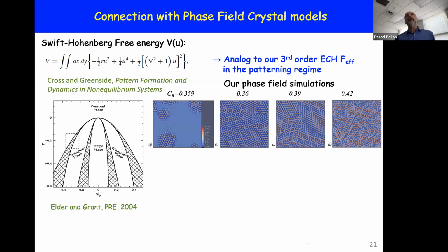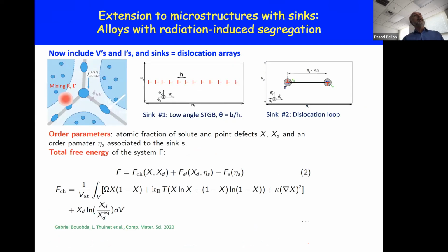In the model that Gabriel is implementing, it's much easier in a sense that in addition to concentration, we also include a field for vacancies and a field for interstitials. So there are those three fields, and then there's one field for the dislocation array. And so we create point defects in a way that's reasonable based on everything that's known in the field of creation of point defects, but in a continuum sense, and assuming that those point defects are isolated. Yeah, there are limitations to that.